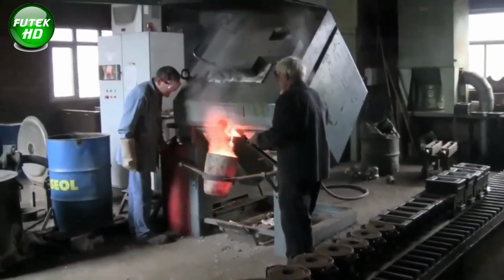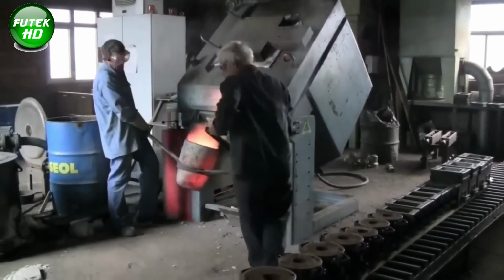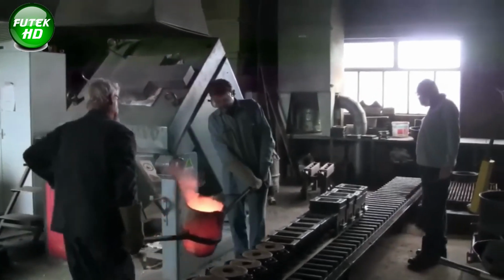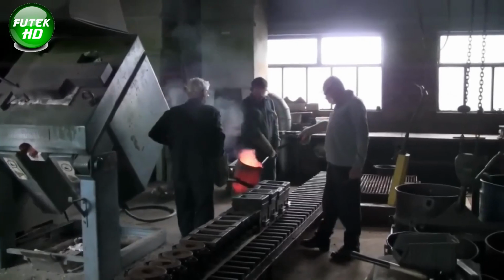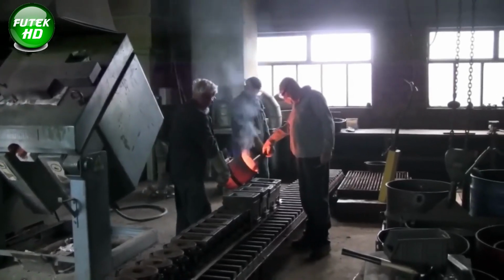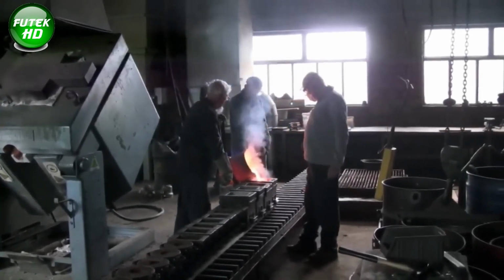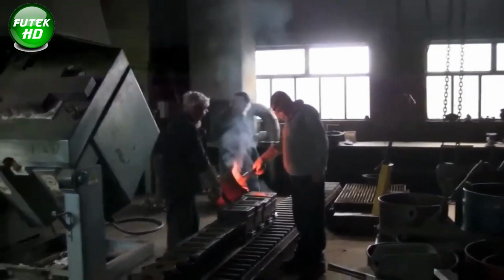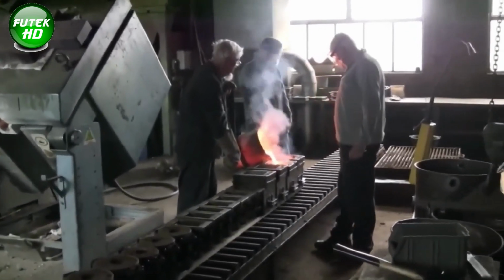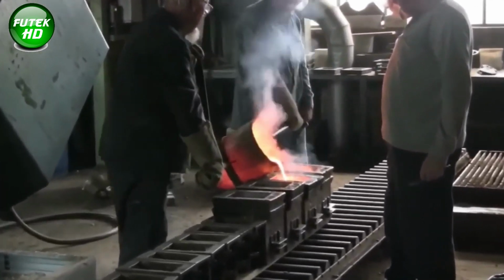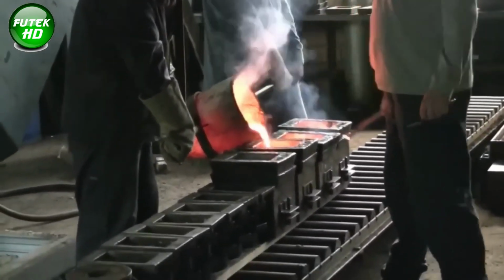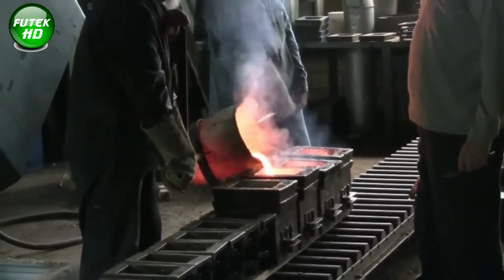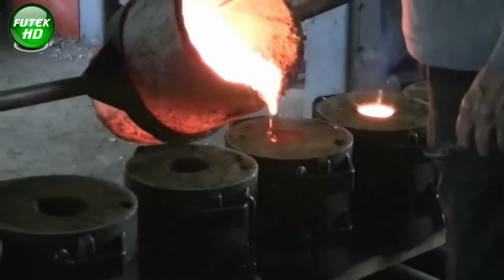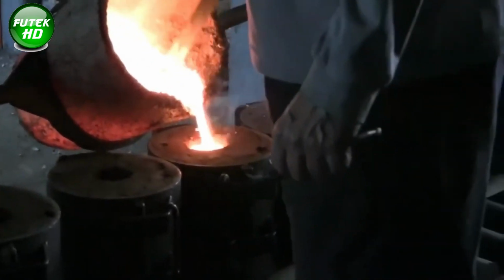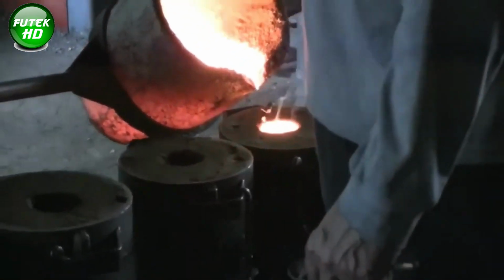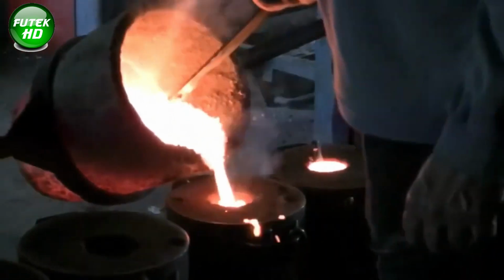As the temperature inside the furnace steadily rises, it reaches approximately 1,280 degrees Celsius, 2,336 degrees Fahrenheit, the optimal point for the metal to become fully molten and ready for casting. This stage requires constant monitoring to ensure the temperature remains stable, preventing any imperfections in the alloy that could affect the bell's quality. Once the metal has reached the desired temperature, the molten alloy is carefully poured into the prepared sand mold.